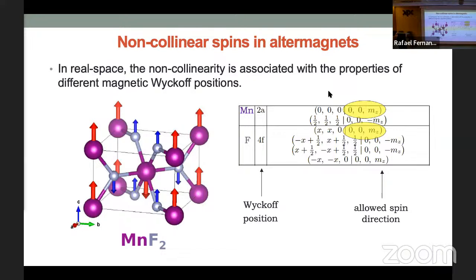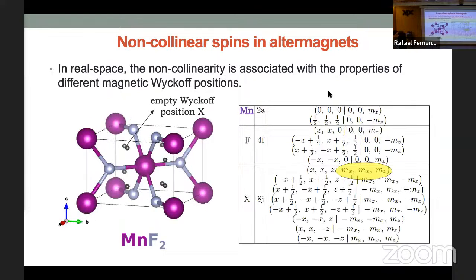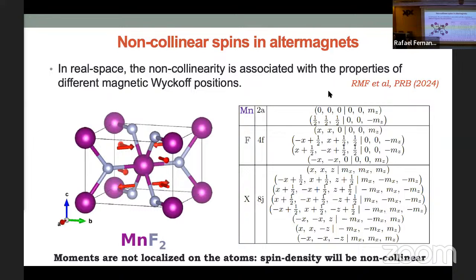Say, oh, wait, I look at the Wyckoff positions of manganese and fluoride, and I clearly see here that the moment can only point along Z. Where is this non-collinear moment? Well, there is another Wyckoff position in this structure that in the case of these rutiles is actually empty. We go here, X. And in these positions, you see, I cannot have moment only along Z. In fact, if you draw the moments, you have this altermagnetic structure I told you about, right? So this is where it is now.